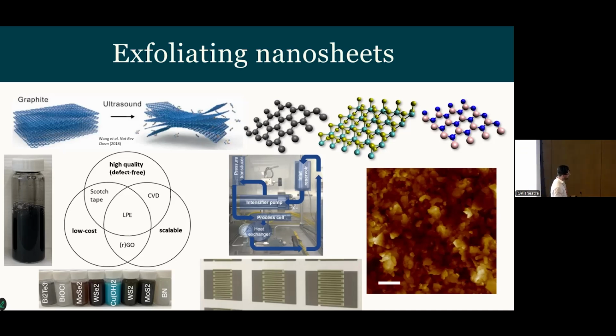What we decided to do, because I've got as much graphene fatigue as anyone, probably more, was actually look at some of these systems and say, okay, we can make graphene, and it's quite well known that you can make graphene by this technique. And you can prove that there are single layers in there, but do they actually have to be single layers? There's a lot of backsliding in the literature in our field as well, where people will quite happily use various grades of graphenes, and they're not actually studying any emergent properties of any kind from the exfoliation.